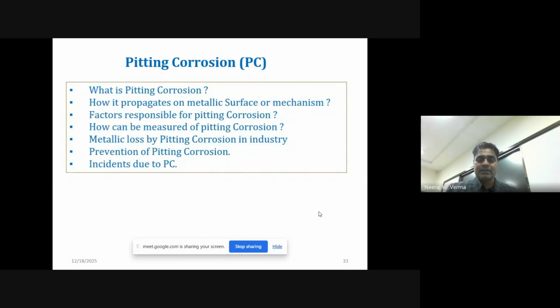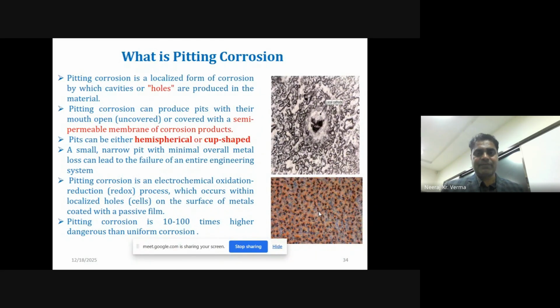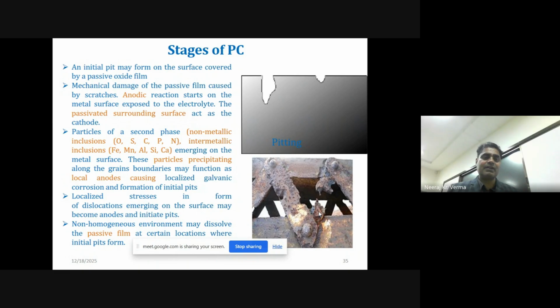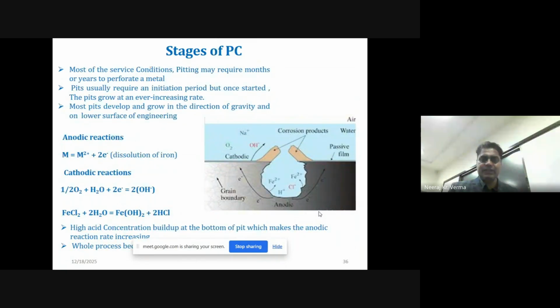Another type is pitting corrosion. Pitting is also a big concern, and pitting is basically just small holes in the structure. When you look with the naked eye, you can see some points over the surface, and these holes create and eat into the structure. It has been estimated that pitting corrosion is more than a hundred times worse than uniform corrosion. And what is the reason? Pitting usually happens due to metallic and non-metallic inclusions in the steels, and you can see several examples of pitting. When a pit starts at a fixed point, it propagates, and after some time the whole structure usually gets corroded.